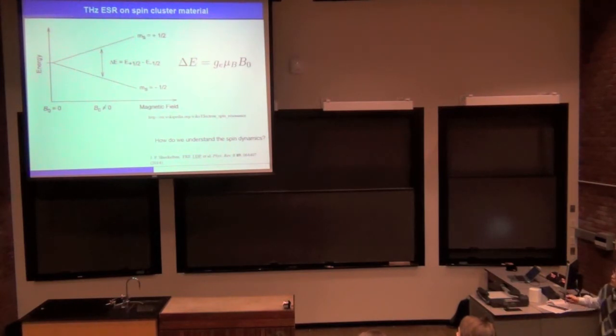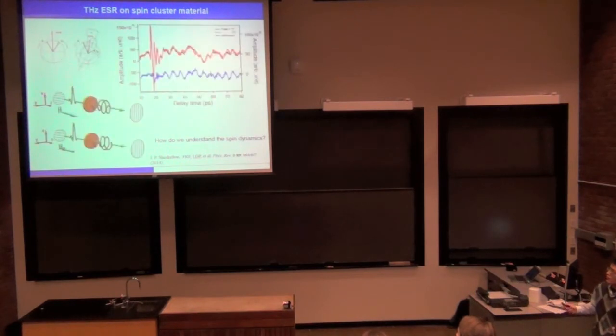As a result, you can have absorption in the spectrum, and the frequency of the absorption would be equal to the g factor times the Bohr magneton times the magnetic field. So from this measurement, what we can learn is information about the g factor. Why is that important? The g factor will tell you a lot about the spin environment. For example, if the spin is anisotropic, for example, if it's Ising-like, then we can measure anisotropy in the g factor. For this situation, g factor wouldn't be an isotropic number, it will be a tensor, so it has different values in different directions. And this is how we measure the Terahertz ESR.